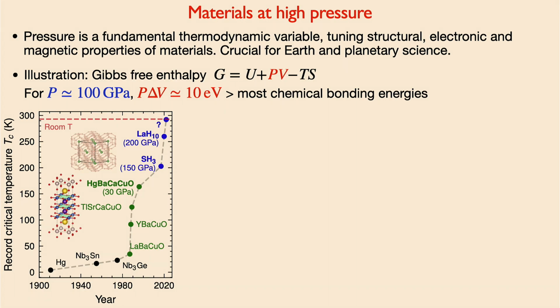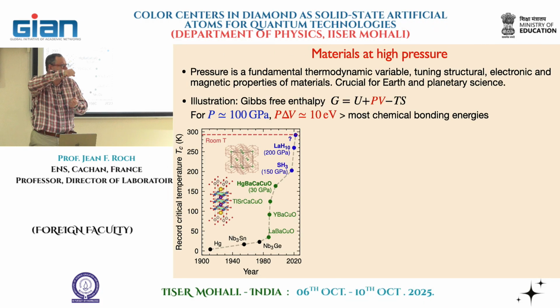Then just after that, a great step was made by Paul Chu and his collaborators in the US, which was to apply pressure on this material. They immediately saw that the TC rose significantly with pressure. So they had the idea that you can mimic this pressure with what they call chemical pressure. You change one atom in the compound, and that mimics the external pressure just by internal constraint in the crystal. They changed the lanthanum atom by a yttrium atom, which is smaller. Going to the smaller size of this system increases the temperature remarkably, above the liquid nitrogen temperature.